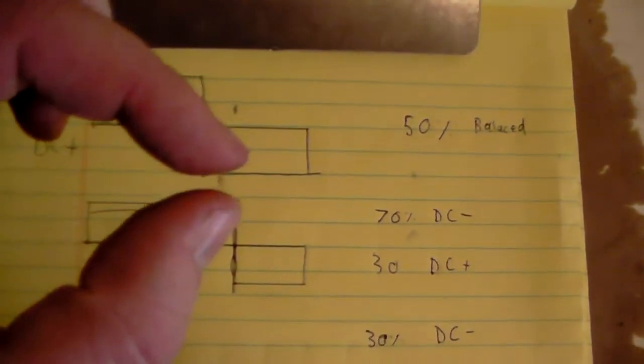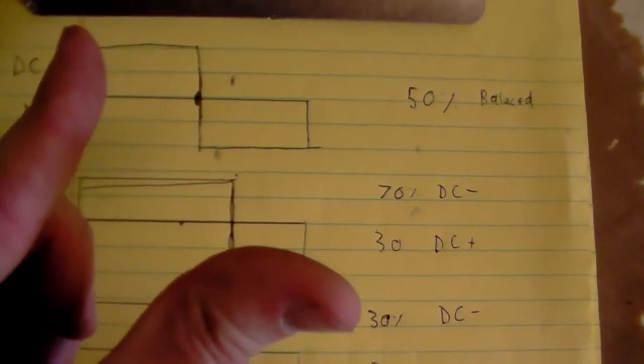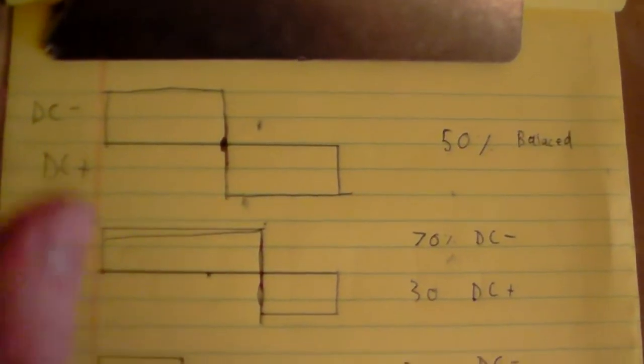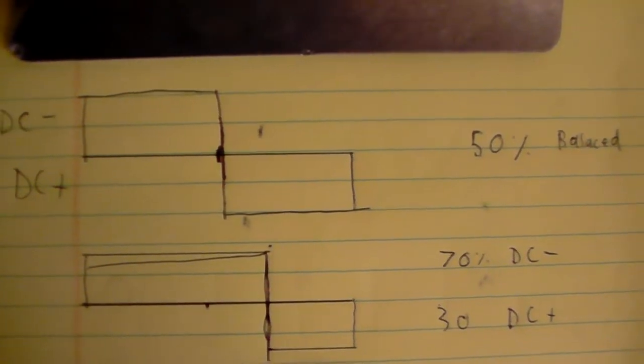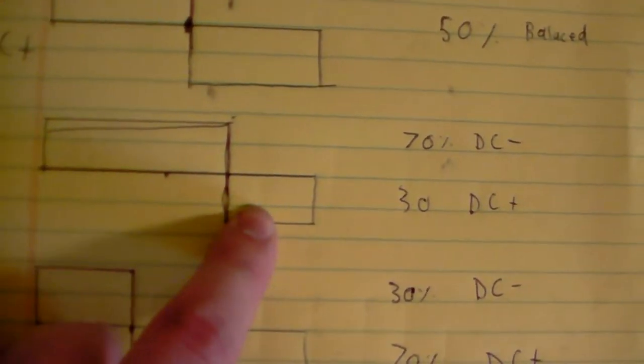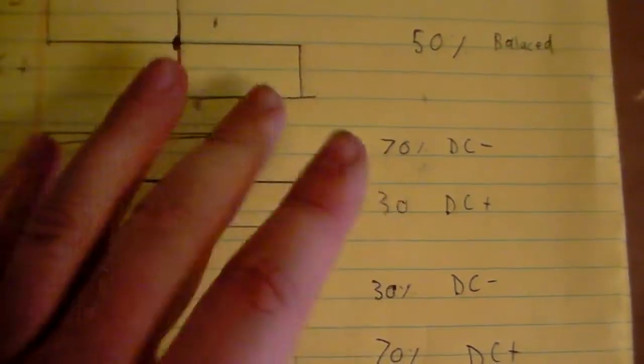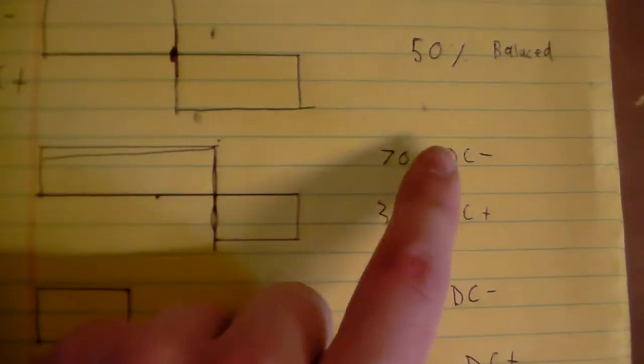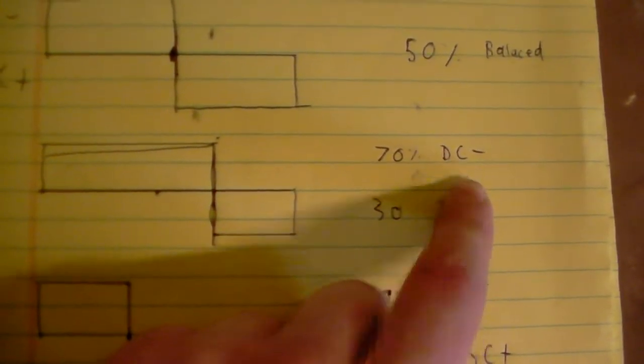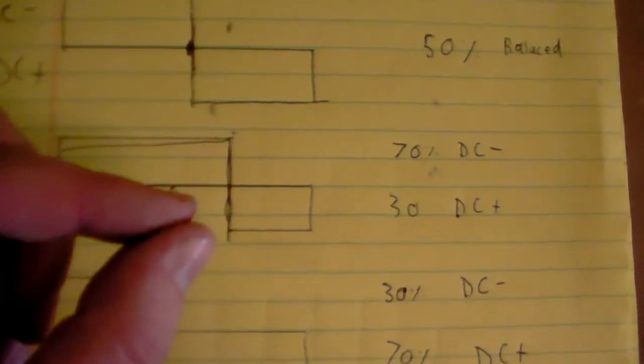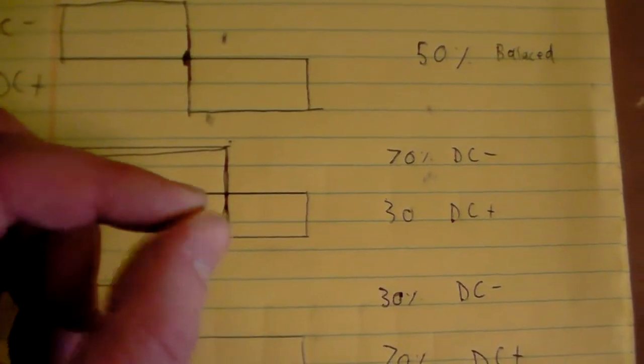Now, as your tungsten balls up, it is going to widen the cone of that arc. So, the more balled up your tungsten is, the wider the cone of the arc is going to be. That can lead you to some troubles when you're trying to do precision aluminum welding. So, most of the time, you're going to be in basically this mode, kind of give or take depending on how clean your aluminum is. So, you want your balance to favor your DC negative side. This will help keep the tungsten mostly pointed and give you a much more focused and controlled arc. And that's why you want to use this side. So, that should be kind of an overview on balance there. One thing I will say is when you get to welding, you're going to have to play around with this setting a little bit so that you can find the one that works for you.